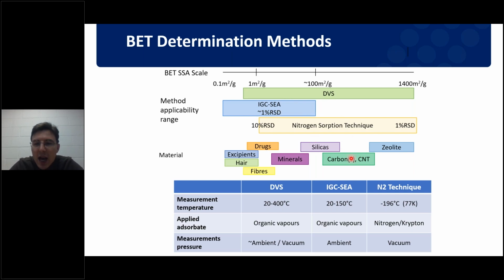And here you can see how it holds up against the more commonly adopted nitrogen adsorption technique, which is a volumetric technique. You can see the nitrogen adsorption technique really excels with high surface area materials. Anything of 100 meters squared per gram, the nitrogen technique does well, especially for materials that are only going through surface adsorption or have a very well-defined pore size distribution. However, there are a few drawbacks to using this technique.